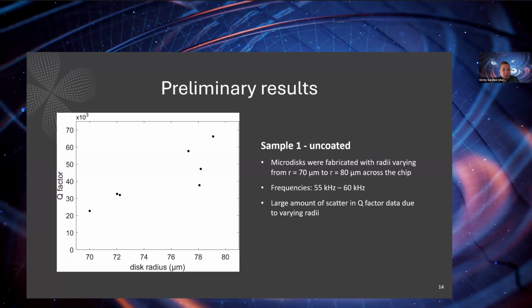So in the last few slides, I'll present some preliminary results from a couple of samples that we've made and measured recently. The first sample is the one that I showed earlier, where half of the sample was coated in titanium dioxide and half of it was left bare. As I mentioned, no two disks on this chip were identical, so the radii changed from 70 to 80 microns across the chip. And the frequencies of the disks changed from about 55 kilohertz to 60 kilohertz.